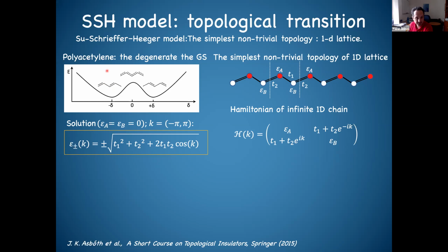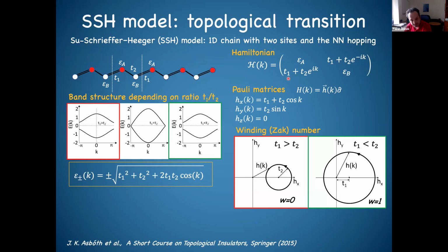So if I go from one phase here to the other one, it's just the continuous change of the ratio of T1 and T2. Basically, I'm alternating the single bond to the double bond. Doing that, I can also plot the band structure, which is very simple. And from the first point of view, what you will find is that if T1 is bigger than T2, I will get this kind of band, which has a band gap. Then if I start to change gradually T1 toward T2, there is a special point where, in the case of T1 equal to T2, you will get the metallic state. And then if I continue increasing T2, again I open the band gap.